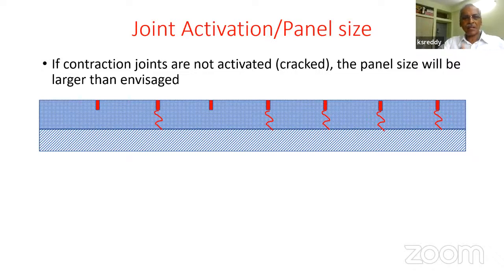So in many cases, many of these pavements actually have panels of size which are much larger than what we thought we were creating. What we thought we created was a 3.5 by 4.5 meter slab, but what we're actually creating, because there is no crack forming below the groove, which we call activation, is not happening. So we are creating larger slab sizes.